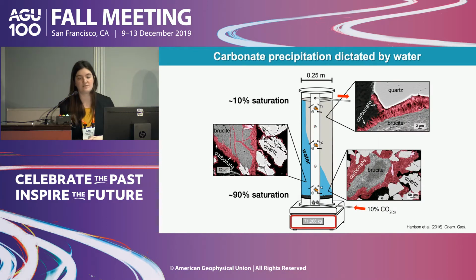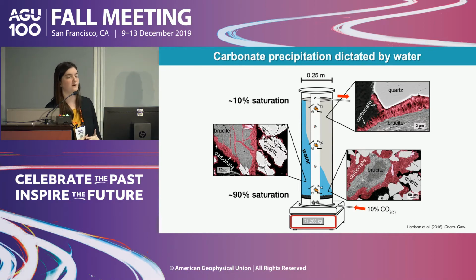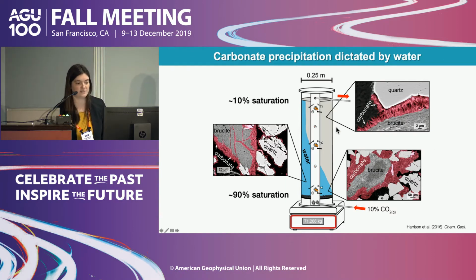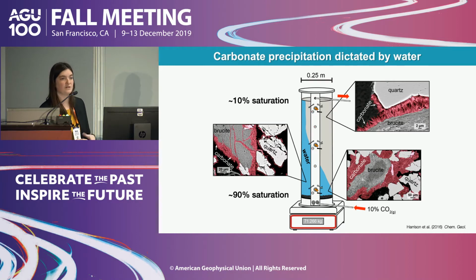What we observed is similar to what we expected. Essentially the amount of carbonate precipitation was strongly dependent on the distribution and availability of water. For example, as shown here at the base of our columns where we have high water saturation, we observed extensive carbonate precipitation occurring throughout the water-filled pore space, shown in this image on the lower right, where carbonate has been false-colored in burgundy. In contrast, in the upper dry regions of our column, shown in the upper right, carbonate was only observed to form as these very thin, flaky rinds, about 4 microns thick, surrounding both brucite and quartz grains.